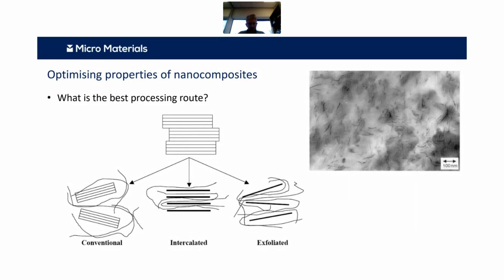If we think about a nanocomposite, it has lots of useful properties, and you have a polymer matrix, but you might want to improve its creep resistance and stiffness. One of the ways that's commonly done is by introducing fillers. In this case, we're seeing rather schematically that a conventional filler, in this case illustrated for clay tactoids, is shown there on the left. So you're getting some polymer chains, there's some breakup of the structure, but not much, and most of those polymer chains are basically not affected by that filler. So you can put quite a lot of filler in there and it's not doing so much for you.